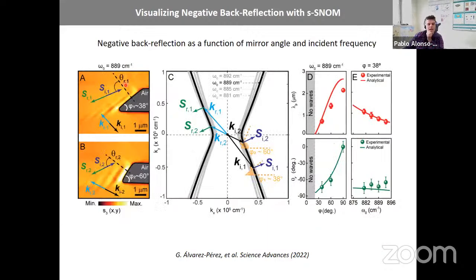We could change the angle of the mirror, and then what we see is that the S vector and the K vector, they are changing. You have a certain tunability of the angle of reflection. But here you need to be careful, because you need to, on one side, see what S is doing and what K is doing. They are not in the same direction. This is all indicated here in this hyperbola.